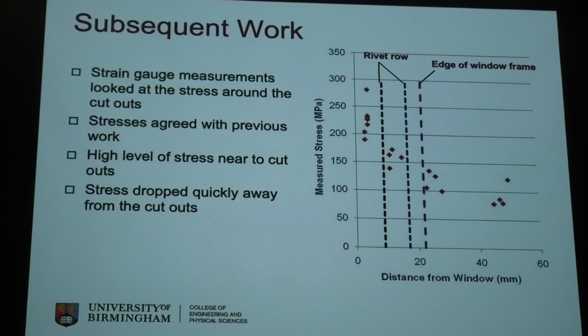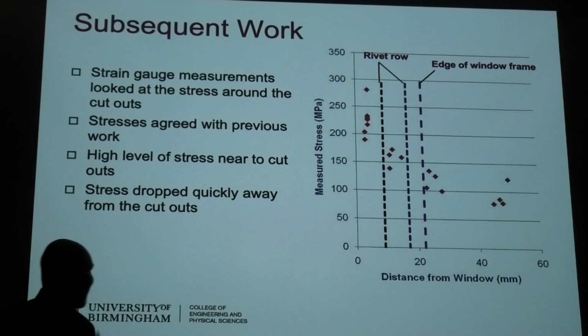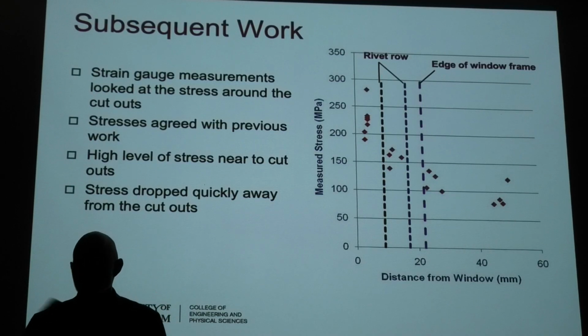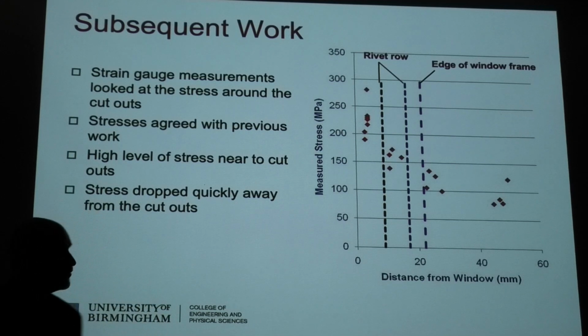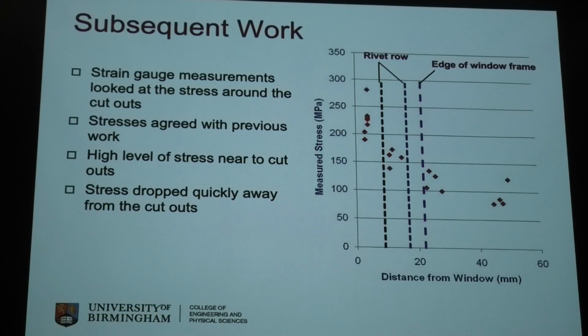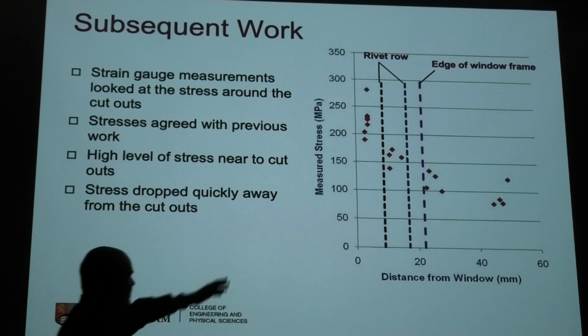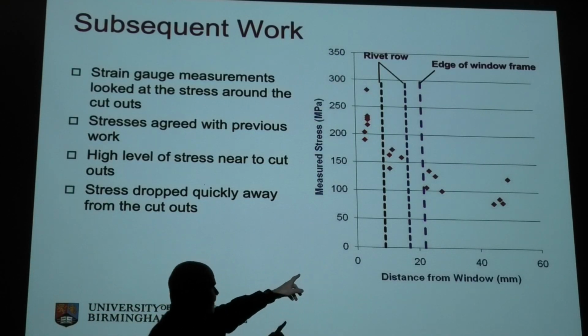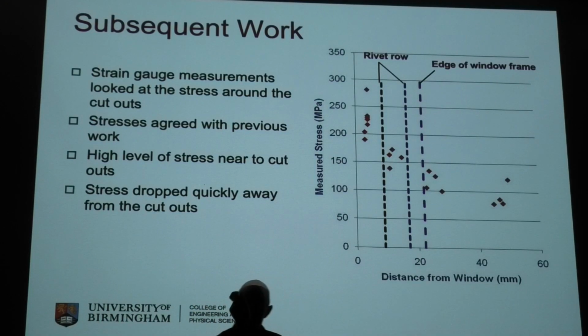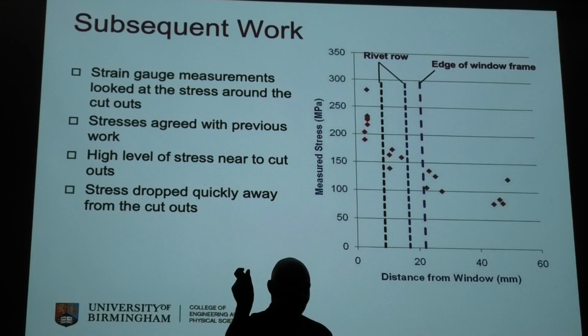What's interesting, I flicked through those screens quite quickly, and also the accident stuff. The failures that were seen were not from that first rivet row closest to the window, they were from the outer one. What tended to happen was that any cracks that formed in the first rivet row either grew into the window and were about that long and therefore stopped,